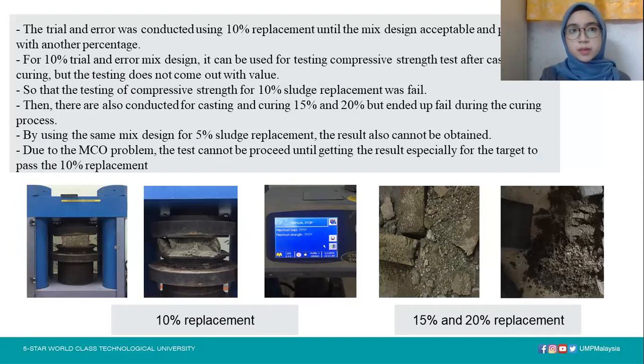For the 10% trial and error mixed design, it could be used for testing compressive strength after casting and curing, but the testing did not come up with a value. So the compressive strength test for 10% replacement failed. Then casting and curing were also conducted for 15% and 20%, but they ended up failing during the curing process. By using the same mixed design for 5% replacement, the result also could not be obtained.